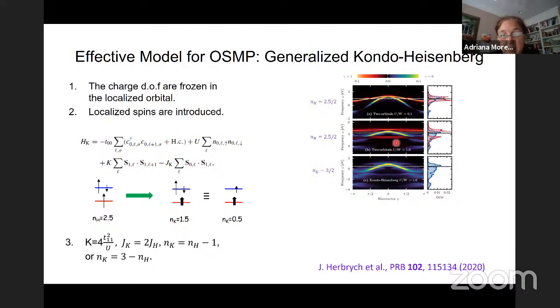And here, with the two-orbital model at 2.5 doping, we see how one of the orbitals becomes a Mott insulator, splits in two—this is the red spectral weight here—while the other remains metallic and determines a Fermi surface. And these are the equivalent results that we obtain with the Kondo model in this situation. So you see how we capture very well the behavior of the metallic orbital.